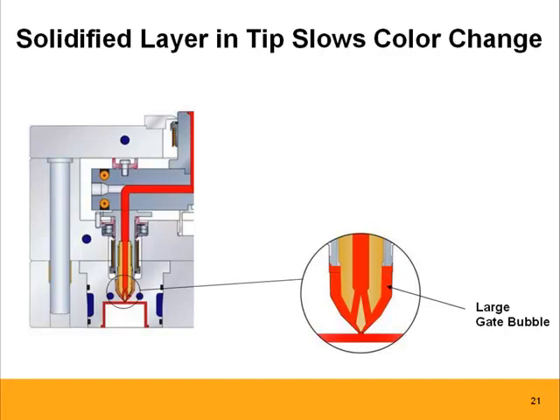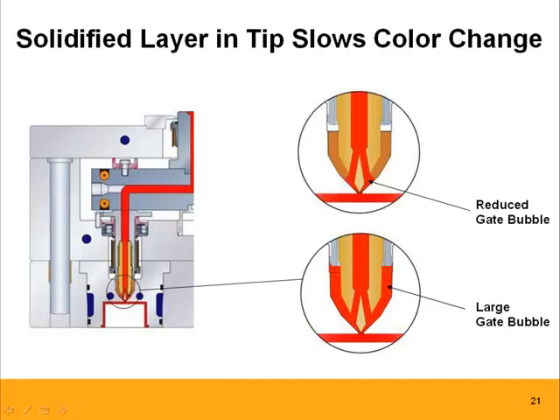So we need that insulating layer, but if we shoot first, for example, with a red material and then want to follow up with a yellow, you can imagine that red material sitting in this area will be sitting there for a long time and keep bleeding into the cavity. A better way of doing this is using a so-called insulator. It's typically a thermoset material, and it gets put in a space where normally the resin would be. By doing so, we're reducing the bubble significantly. You can see there's a big difference between this gate bubble and this gate bubble. That's a lot easier to flush out when we follow up with a new color, for example yellow or something else. So for an optimized color change, a reduced gate bubble is a preferred option.